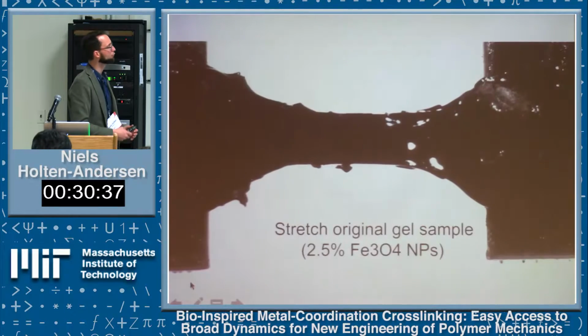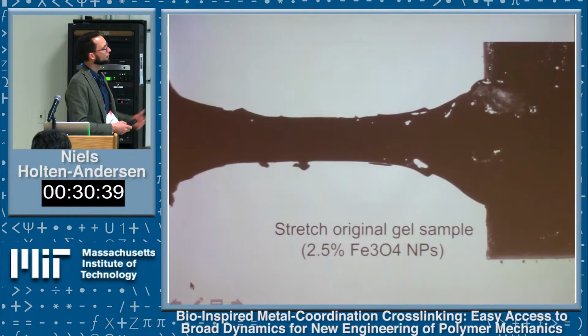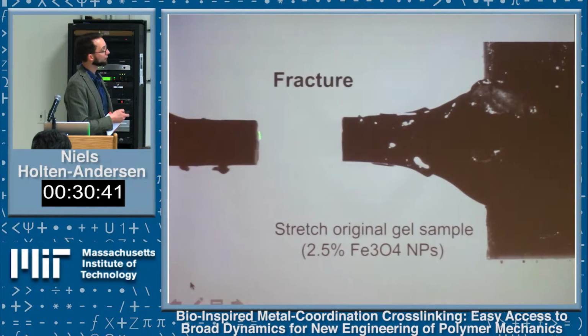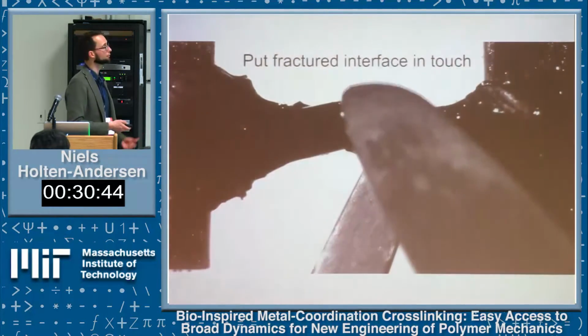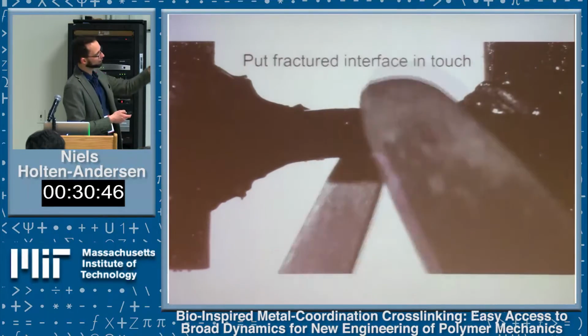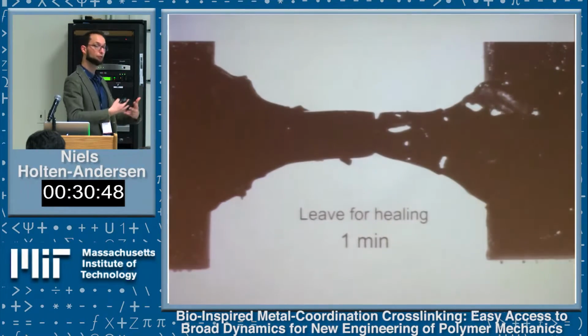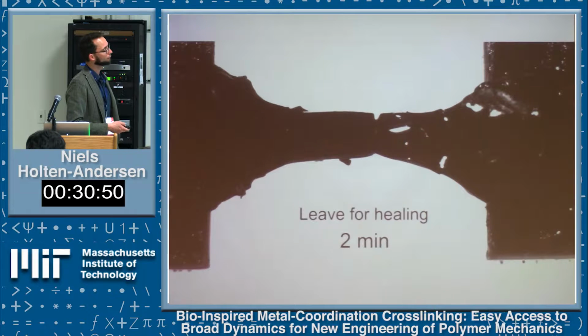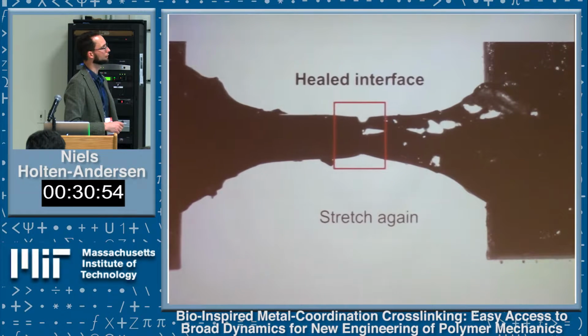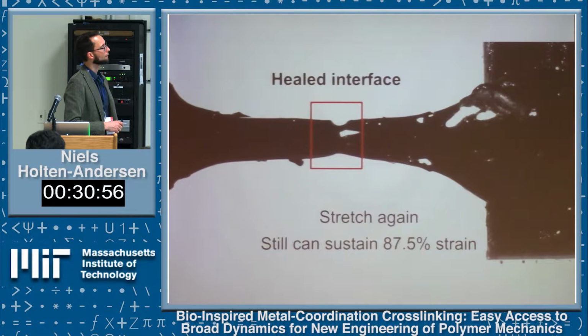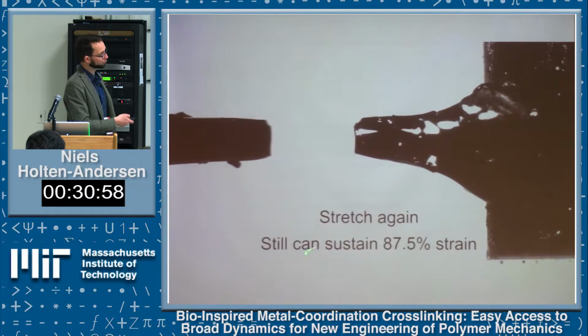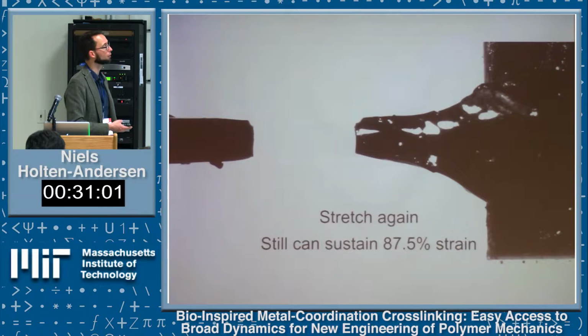This is real time, so we pull on it the first time. The material will break somewhere right there, and you can see it does break like a solid-like material. Xiaochu will then just qualitatively put it back together, let these two surfaces reheal for a couple of minutes—he doesn't do it perfectly, that's just a qualitative demonstration—and we pull it again, and it'll actually go up to almost 100% strain within just a couple of minutes of recovery.